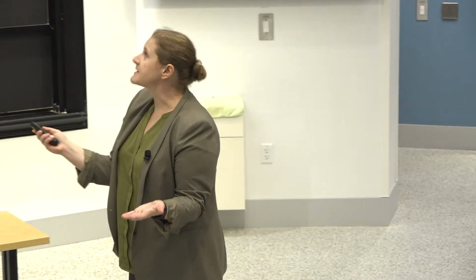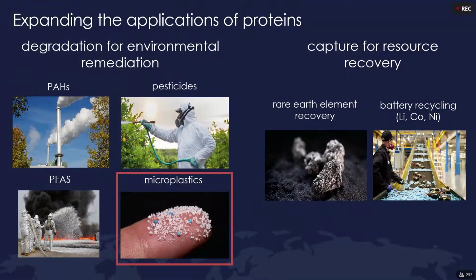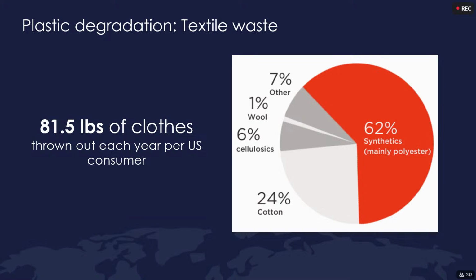So what else can we do with proteins that have already been evolved naturally? Something I found out when we were thinking about plastic recycling is that people in the US throw out about 80 pounds of clothes per year. That is an enormous amount, and that is not what you donate. This is what literally ends up in landfills. And about 60% of all the textile waste in the US is polyester. So it's a good target, right? If we can degrade about 60% of textile waste, we can make a significant impact on the amount of waste produced.